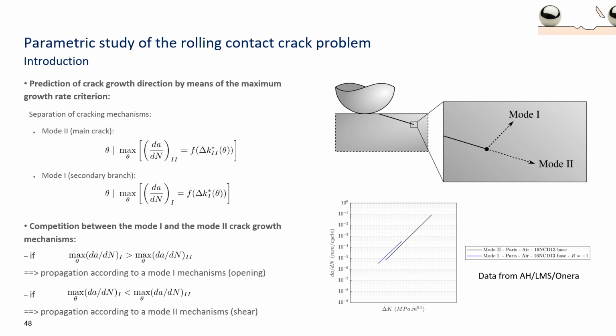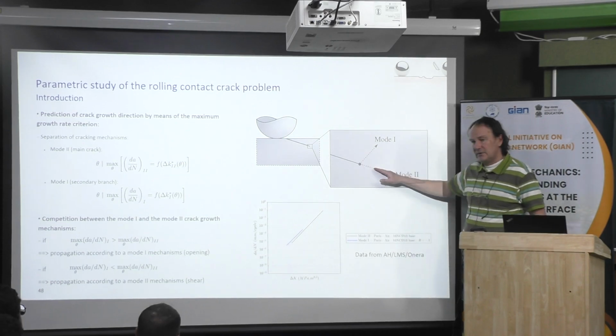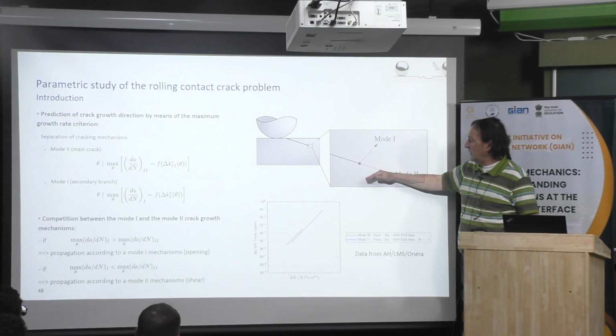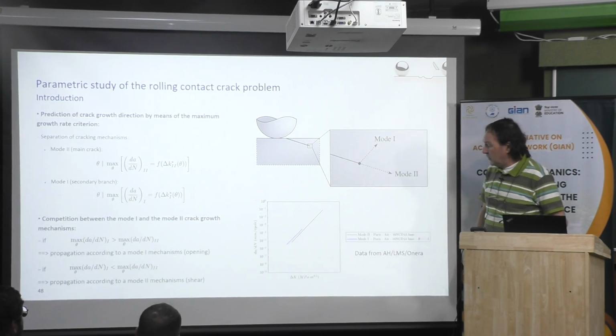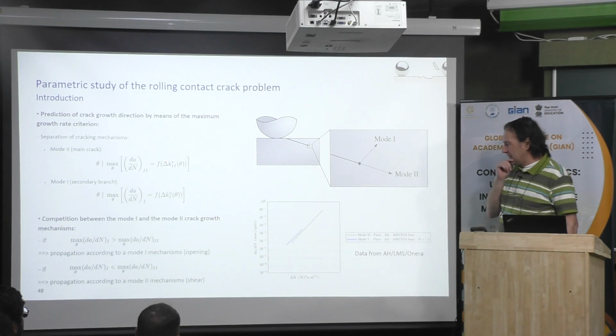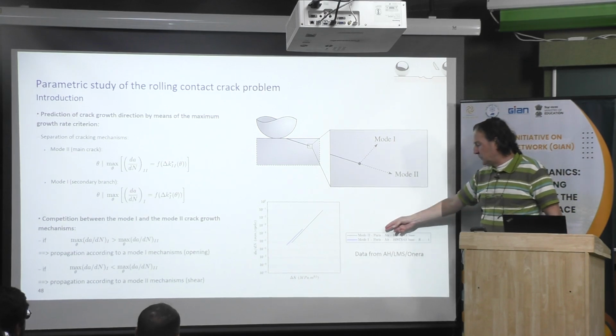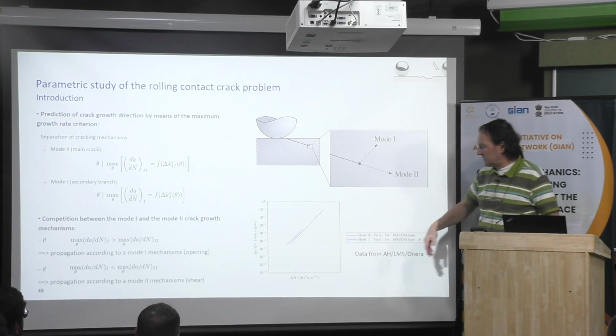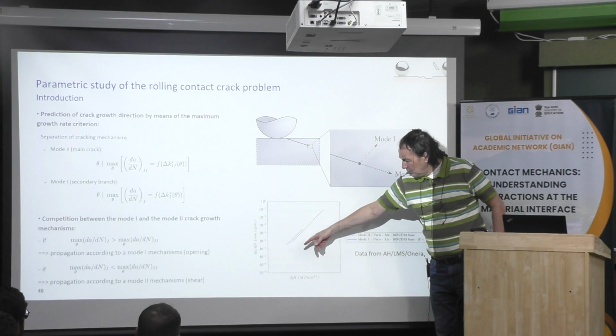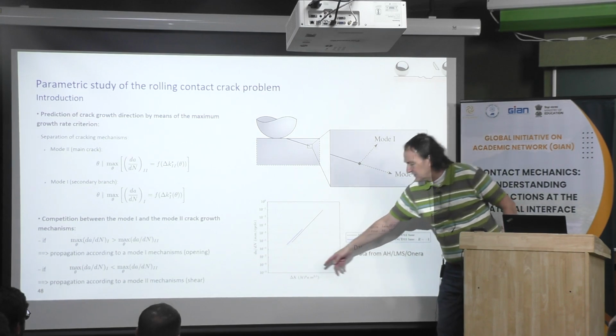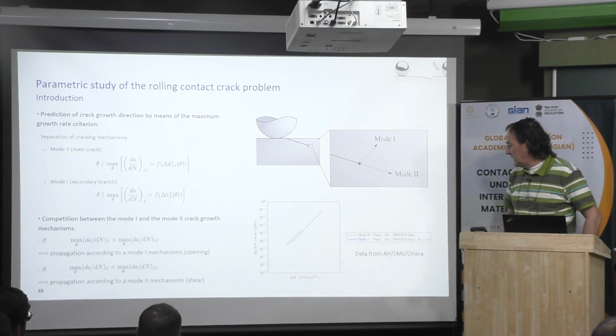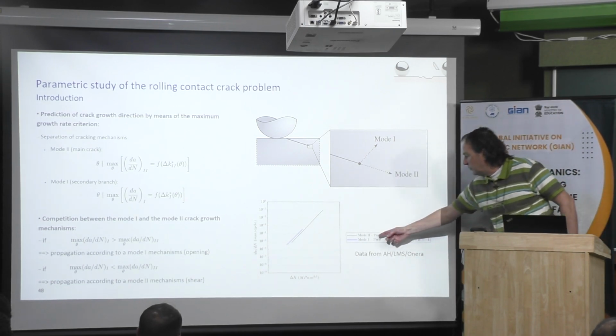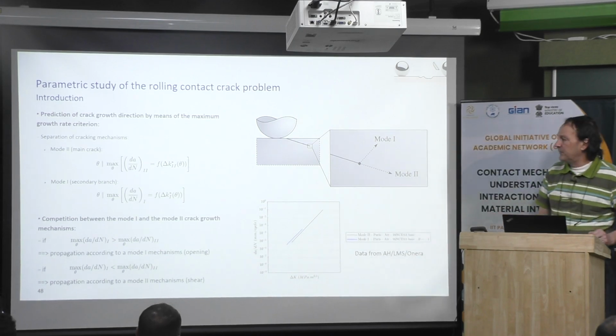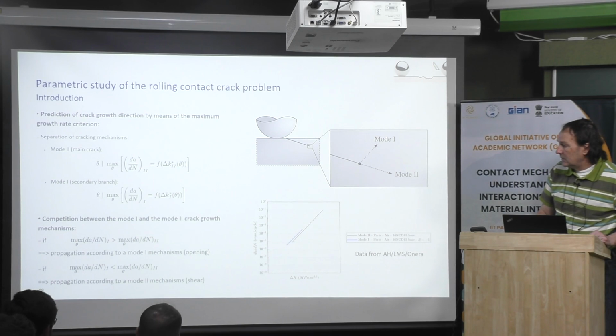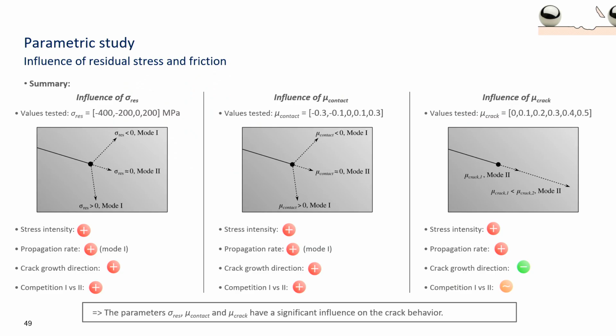When you have mode 2 propagation, the crack is propagating straight. When you have mode 1, it will branch to the top or to the bottom. For the crack propagation model, we use some data from another lab in Paris. They did experiments with the same materials, and then they provided us some curves. We are not allowed to give the data. You can see there is no scale for the abscissa. But, okay, this is for mode 1 and for mode 2. Then we have the material properties. Then we can choose between mode 1 or mode 2 depending on the results.